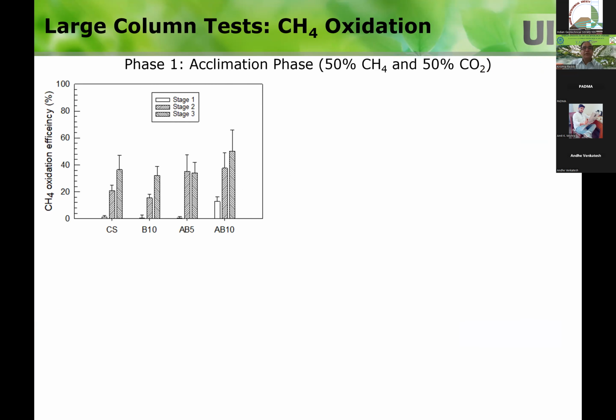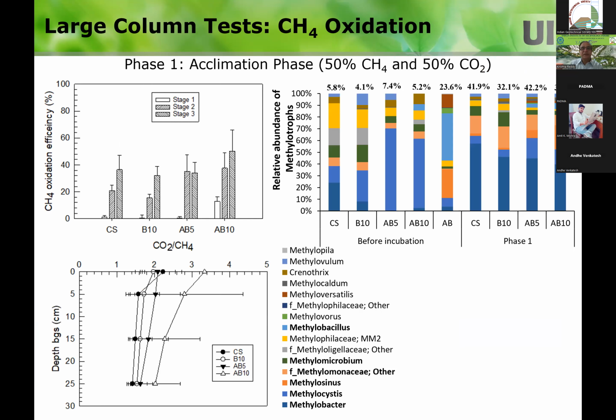So I'm not going to go into a lot of details about this one. You can find a lot of papers. So at different stages, stage 1, stage 2, stage 3, in the column experiments, you can see how much of the methane oxidation there is. Stage 1 is the acclimation. Initially, you don't have methanotrophs, so the oxidation efficiency is low. And in stage 2 and stage 3, you see the oxidation rates have gone up. And that is also clear from the gas profiles you see here.